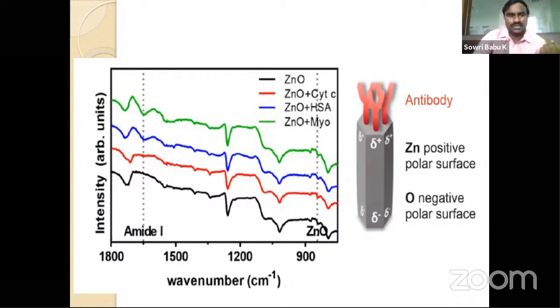So what we have done is, as I showed you in the previous slides, zinc oxide has an isoelectric point of 9.5. Right? So we have selected three proteins. One of them has an isoelectric point greater than zinc oxide, and two of them have an isoelectric point less than zinc oxide. That means they are less positive. Suppose I take cytochrome C, which has an isoelectric point greater than zinc oxide, that means it has more positive charge. Similarly, if we take HSA or myoglobin, they have less positive charge.